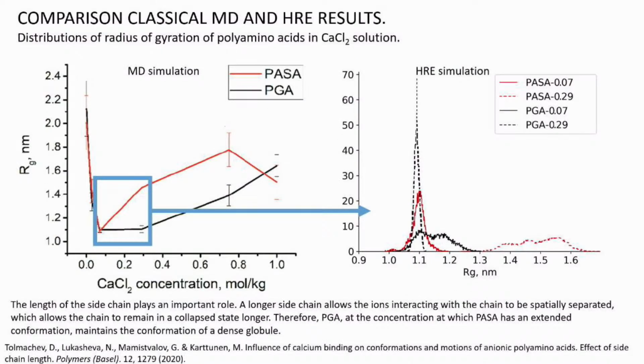And first of all, we had to choose the systems for the simulation, and we chose 2 concentrations. First of all, the minimum of radius of gyration for aspartic and glutamic acid, and second, the concentration when the difference between aspartic and glutamic acid appears. Here we can see the distribution of radius of gyration. And we can see that there is a big difference between aspartic and glutamic acids.